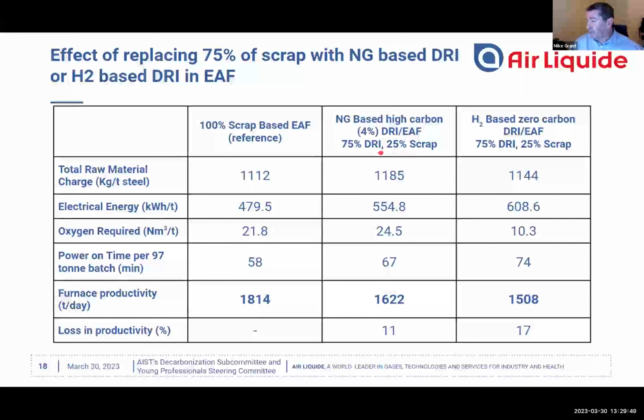If we go further and replace the natural gas reductant with 100% hydrogen, now we're making a DRI that has no carbon in it anymore. And so it's going to be more difficult to melt it in the electric arc furnace. We'll have to back off on our oxygen in order to maintain our yield. And we see this chemical energy is no longer available, so we have to melt with more electrical energy, and we lose another 6 or 7% productivity. So this is one of the issues we're going to have to deal with when we start using electric arc furnaces to melt DRI.